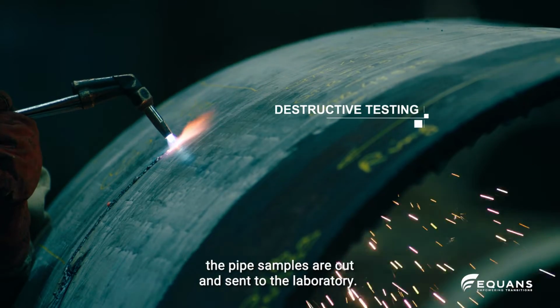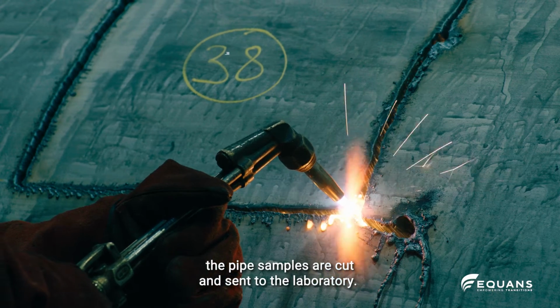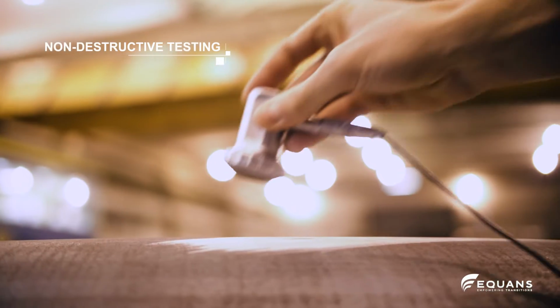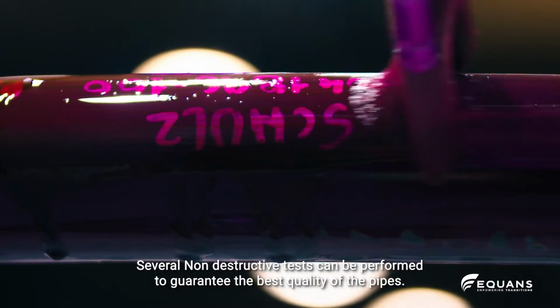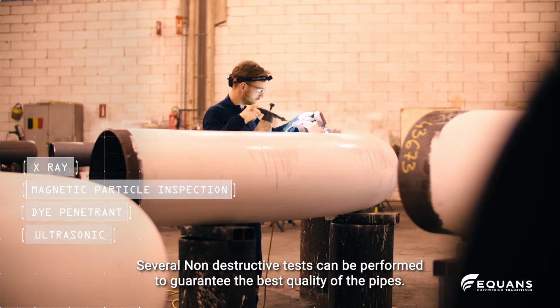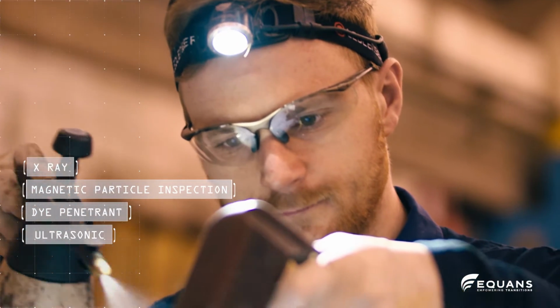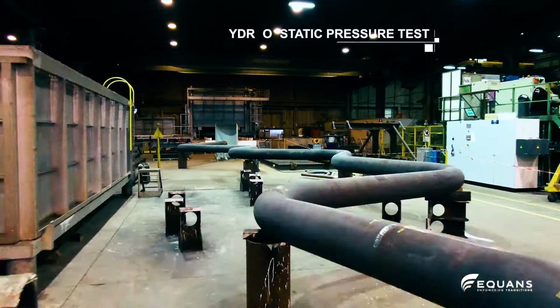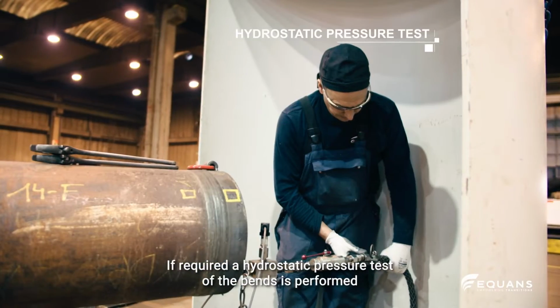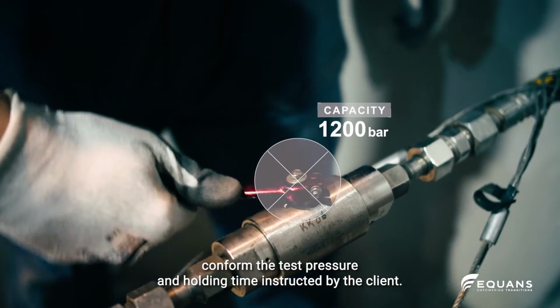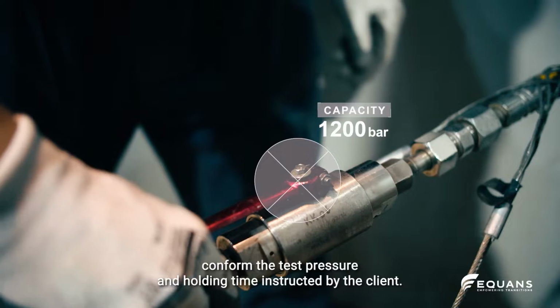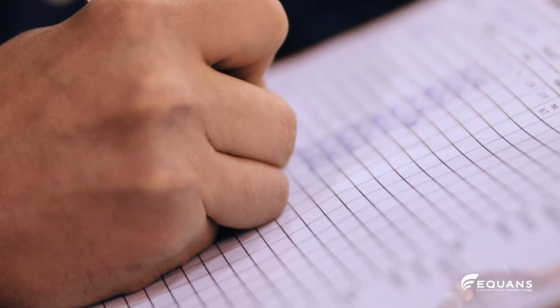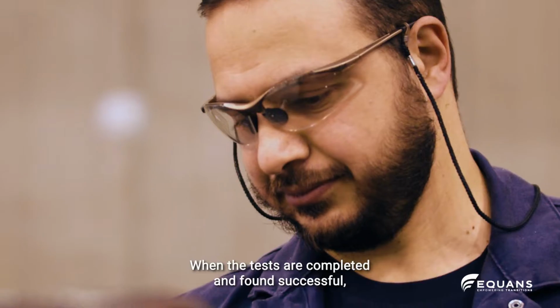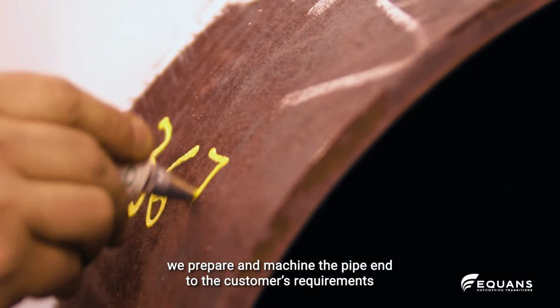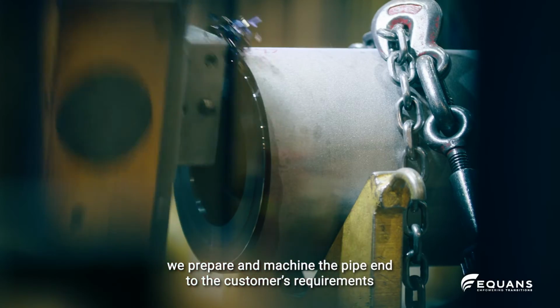If sampling of the bends is required for destructive testing, the pipe samples are cut and sent to the laboratory. Several non-destructive tests can be performed to guarantee the best quality of the pipes. If required, a hydrostatic pressure test of the bends is performed, confirming the test pressure and holding time instructed by the client. When the tests are completed and found successful, we prepare and machine the pipe end to the customer's requirements.